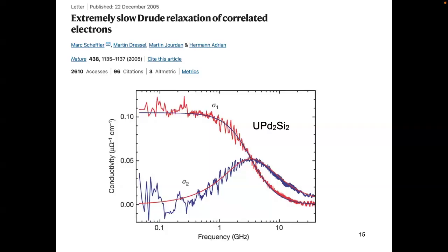Directly measured. That's right. In this, they're reasonably directly measurable. There's no Kramers-Kronig performed here, if that's what you're asking about. Yeah, well, I think you can see that here in the sense that you fit with a Kramers-Kronig consistent form. The Drude response is Kramers-Kronig consistent. So the smooth curves are Kramers-Kronig consistent, and so the data is Kramers-Kronig consistent to the extent that those curves are a good fit for the data. I would put it like that. We don't often go back the other way, but you certainly could.